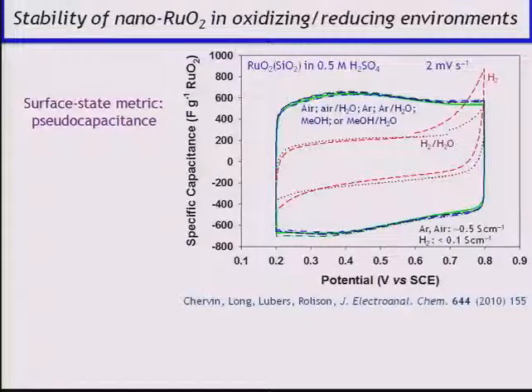So we wanted to ask how stable was so little ruthenia on the paper as a function of atmosphere, using the pseudocapacitance, the charge stored in aqueous acid, as our metric. And if we expose that ruthenia shell on the paper to air, hydrated air, argon, water-sparged argon, methanol or water-methanol vapors, there's no change in the capacitance.